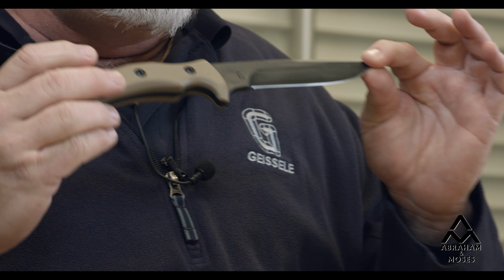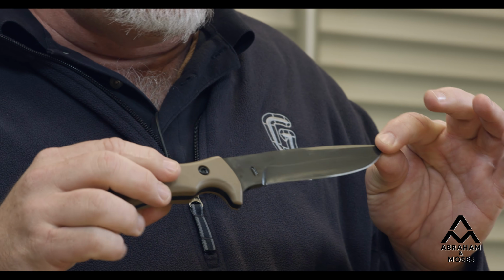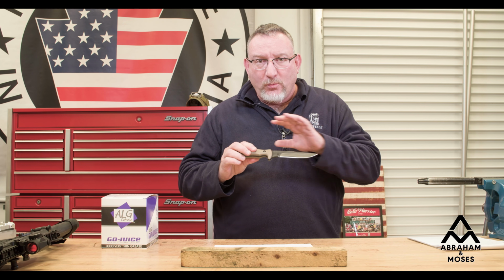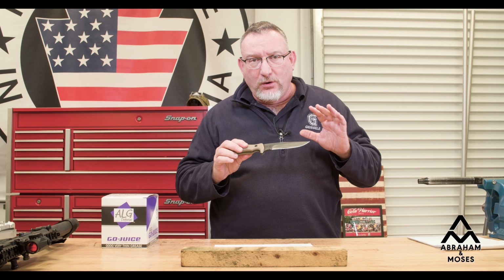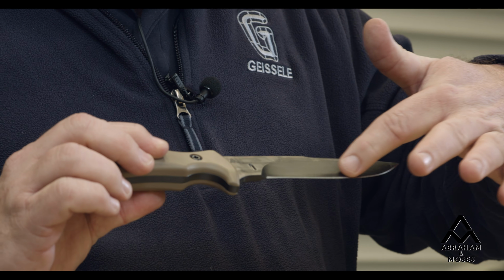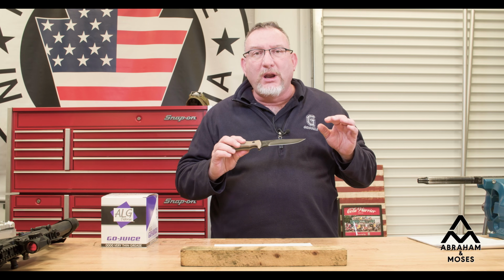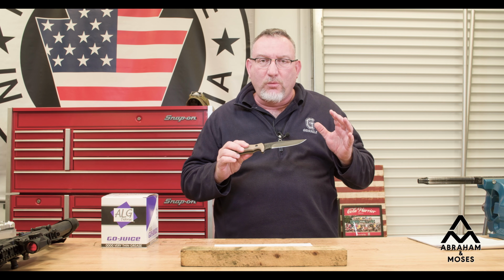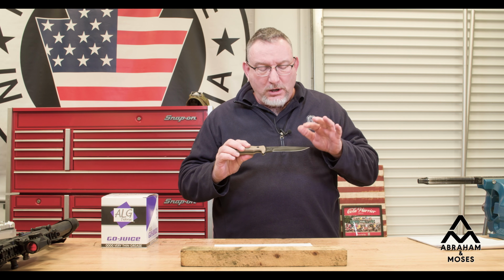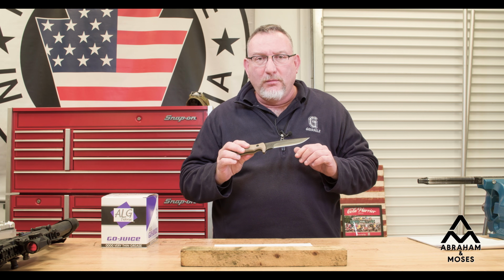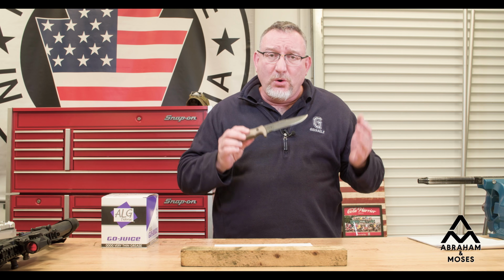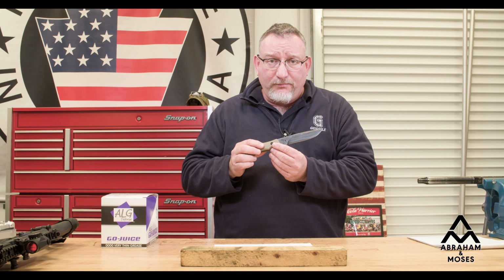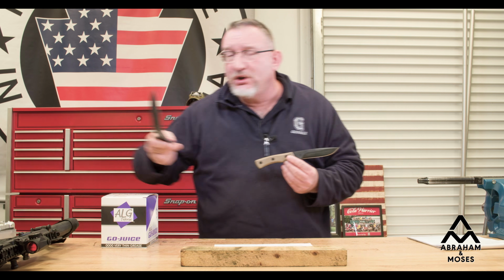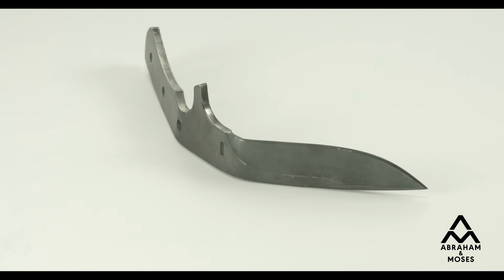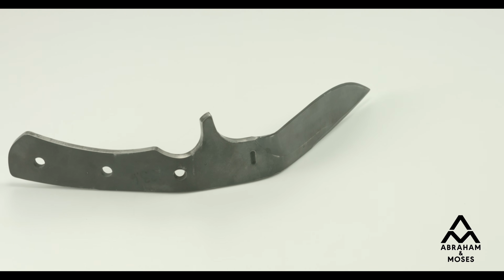And what we do with this is it's differentially hardened. What that means is we take the knife, we harden it, we triple temper the steel. And then we go into the blade right here, and this is brought up in hardness to 60 to 62 Rockwell. So the cutting edge is very hard, where the rest of the steel is very ductile. And then it's tempered 3 times again. So it gets a total of 6 tempers to this steel. And with this, you can see what you can do with it. You can bend it like this, okay? Even though the edge of the blade is extremely sharp.